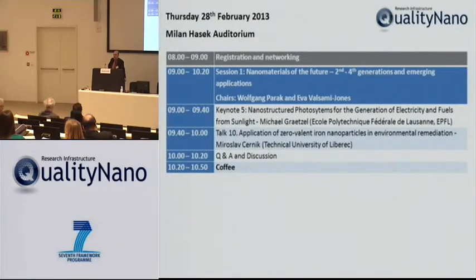Yes, again, Jacques Bouillard from Ineris, France. I've got a question regarding these ionic liquids for these photovoltaic panels. You use ionic liquids, and we found in our laboratory that, whereas we thought the ionic liquids were quite steady and stable, actually they can be reactive and catch fire. So the question is, if you have these panels under the sun, it's heating up to 50, 100 degrees maybe locally. Do you fear any fire problems out of these panels?